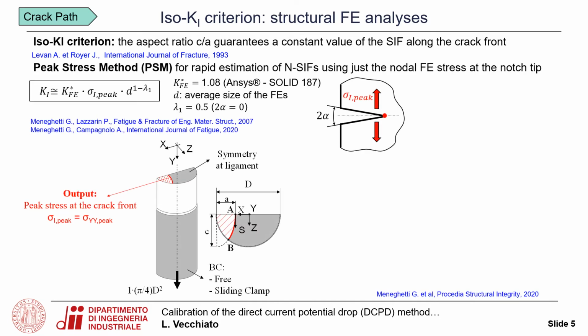According to Levan and Royer, the ISO K1 criterion assumes that the crack shape changes with an aspect ratio which guarantees a constant value of the stress intensity factor along the crack front. In this work, the corresponding crack path has been evaluated adopting the peak stress method, which is an engineering tool for rapid estimation of notch stress intensity factors using just a single finite element stress at the notch tip.